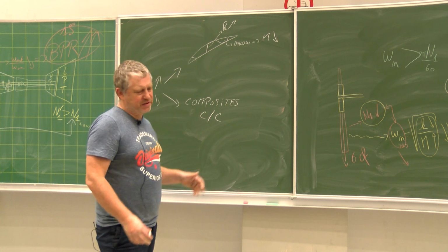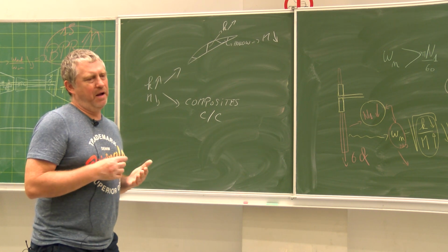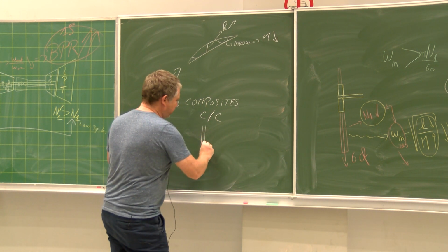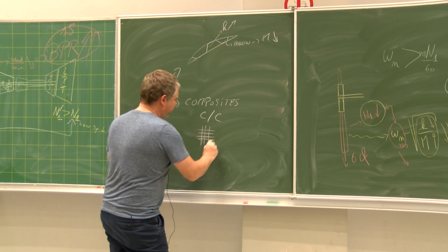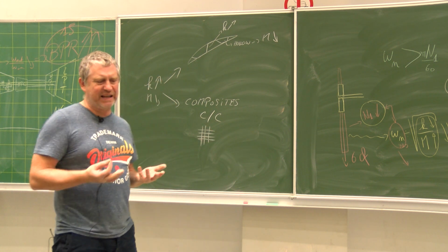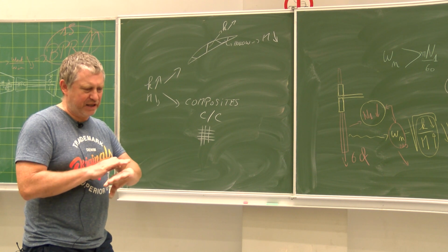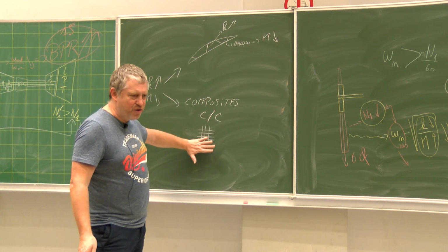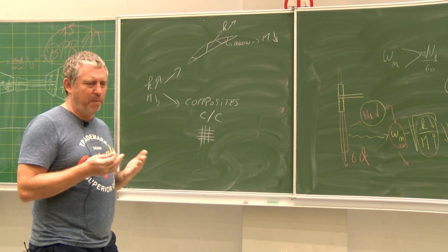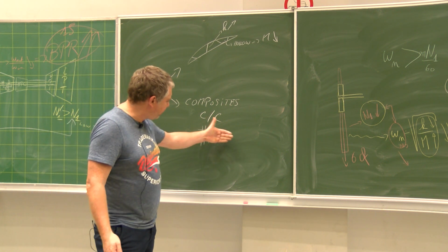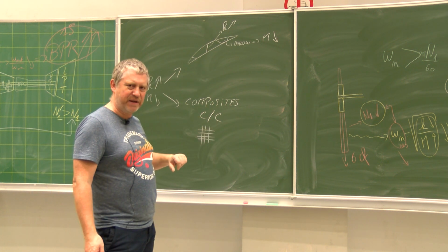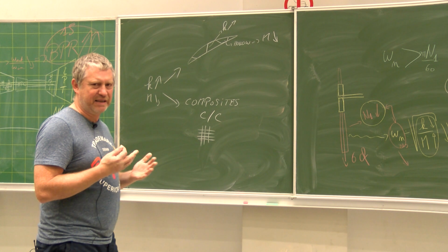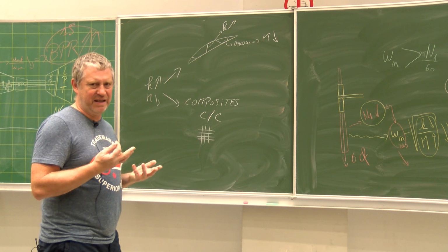And the fibers are made with, let's say, special arrangements, some architecture of the fibers, so that you are going in two different directions, and you have tissues that are already forming the fibers and giving you a stiffness in this direction and a stiffness in this direction. And so you are superposing these layers of fibers that have been prepared in this way.